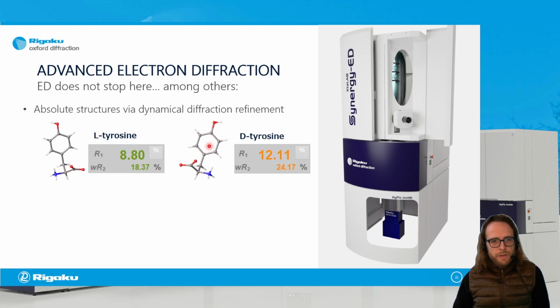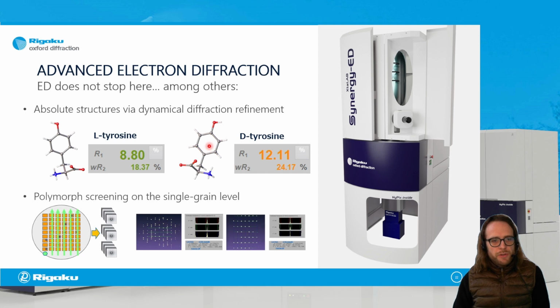Another thing we're working on right now a lot is polymorph screening, because you can also imagine that a sample which contains a lot of these small crystallites is essentially just a powder sample which you measure on a single grain level, which means that if you have a certain mixture of polymorphs or some impurities in your sample, you can really disentangle all of them by measuring them in an automated way on a single grain level.